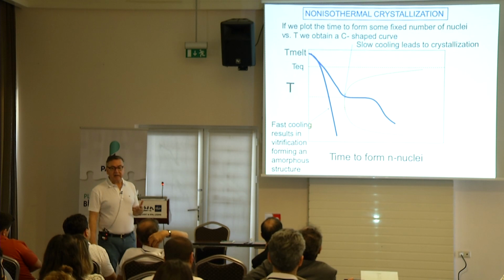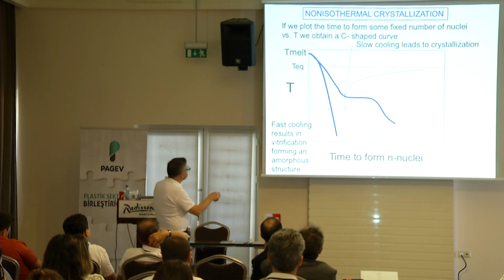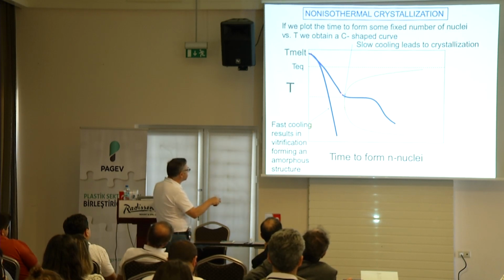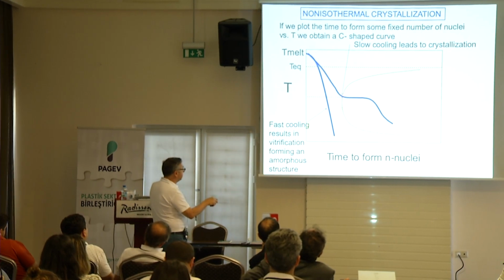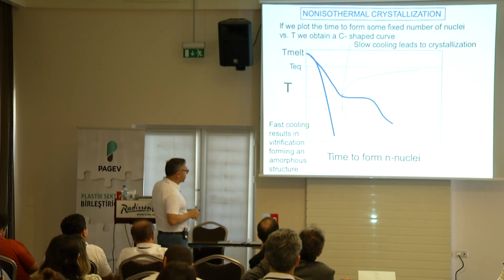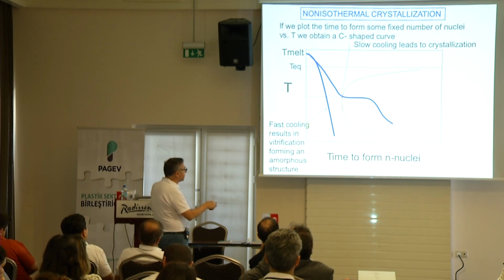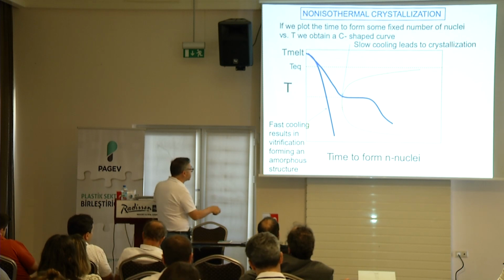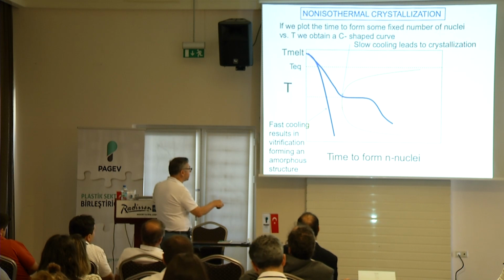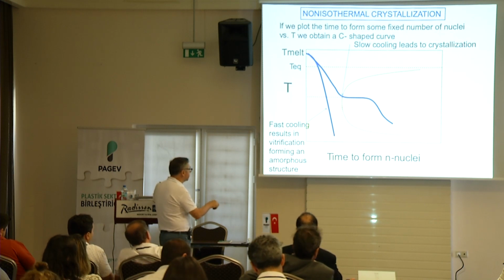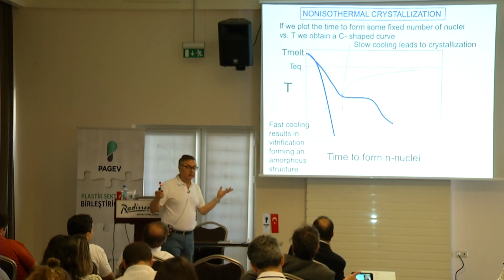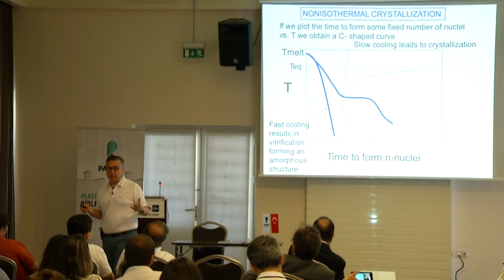So we actually use this to explain the non-isothermal crystallization. Okay, so the material starts at the melt. This is the cooling. And if, during any kind of process, casting or fiber spinning, injection molding, it encounters this curve, it says, well, I have sufficient conditions for crystallization to take place. And you have an energy release because crystallization is exothermic. And then you cool down. But if you cool very fast, like on the skin, then the material basically ignores all of this and goes below the glass transition temperature, and this leads to vitrification. The material becomes amorphous. That's it. It has no chance of crystallizing.